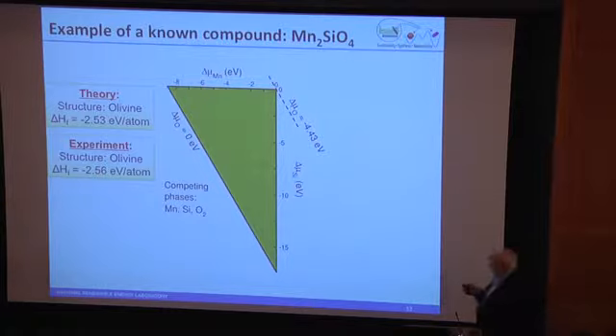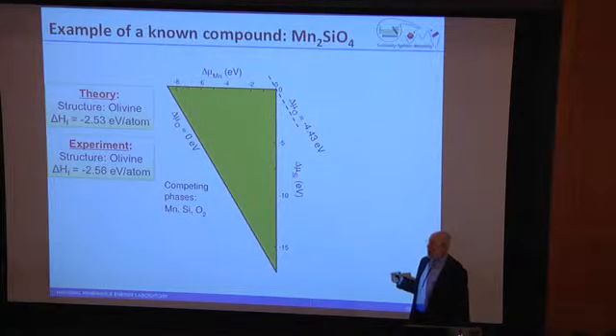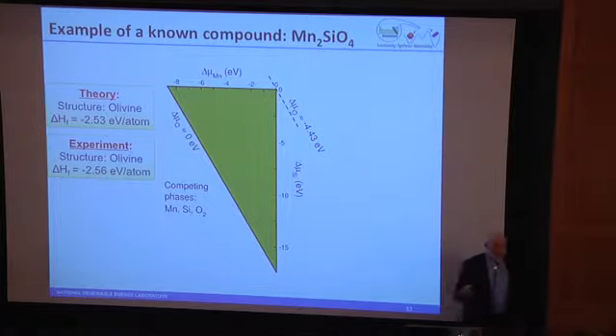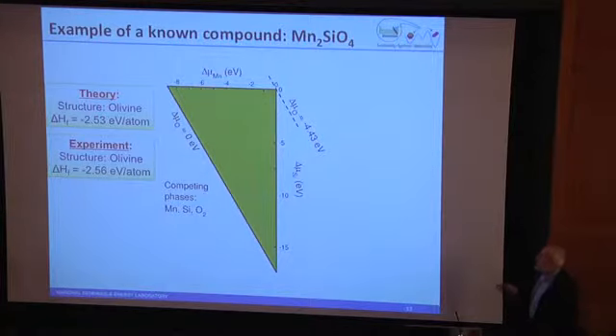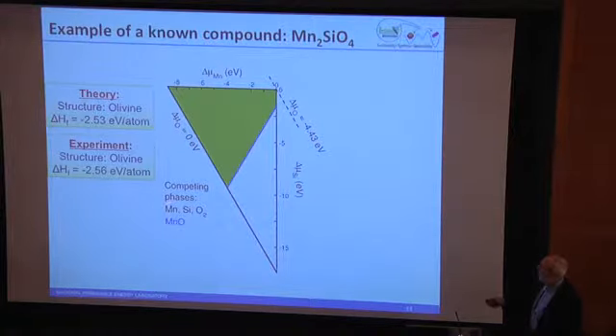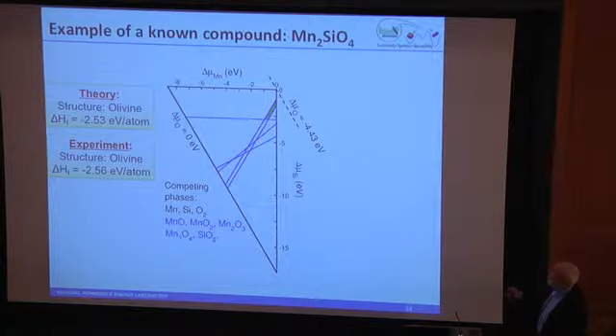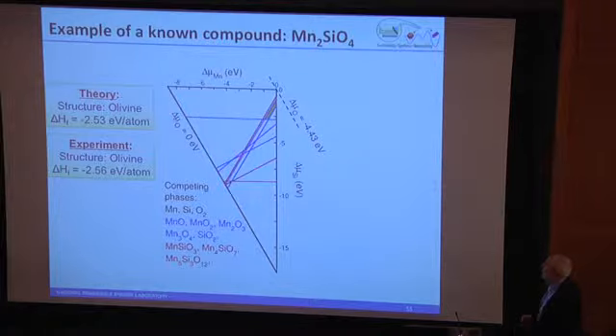So this is where the connection from theory goes to experiment. And this, from my viewpoint, is transformative. So this is calculated, right? As you calculate other phases, so these are competing phases, you knock out a chunk of synthesis space. And ultimately, when you look at the chemical potential for synthesizing, in this case, the Mn2SiO4 olivine, what theory tells you is you ought to only be able to make it in this range. This is the only place where it ought to be thermodynamically stable.